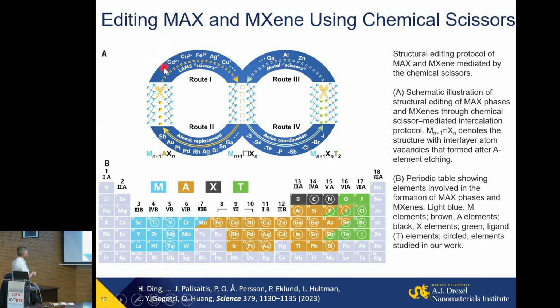We can take MAX phases and use this Lewis acid molten salt as scissors to cut existing bonds and put in virtually any metal element which in MAX phases won't be thermodynamically stable. You cannot make from elements or other sources a MAX phase with these elements because there is always another compound with lower Gibbs free energy. But you can put in the layers other elements, designing layered structures, for example, gold or platinum or bismuth.